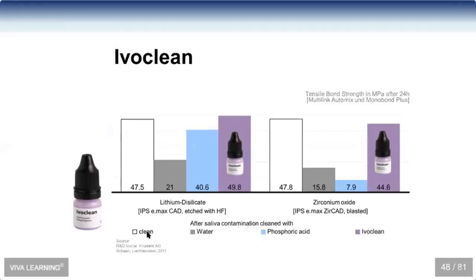So as you look over here, this is a tensile bond strength if you use Multilink Automix and Monobond Plus and cement an Emax crown to a tooth and then pull it off. If you try it in the mouth and contaminate it with saliva and then just rinse it with water, you can see the bond strength drops by about half.